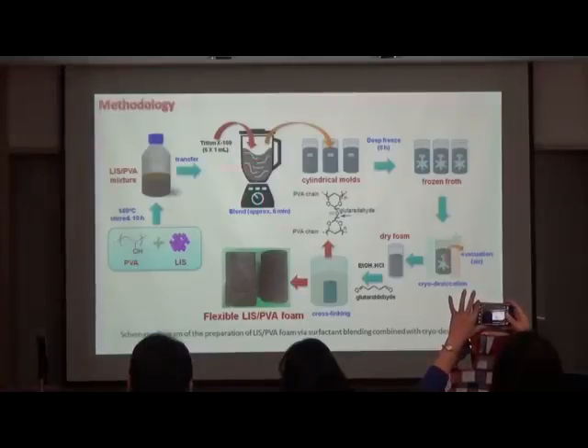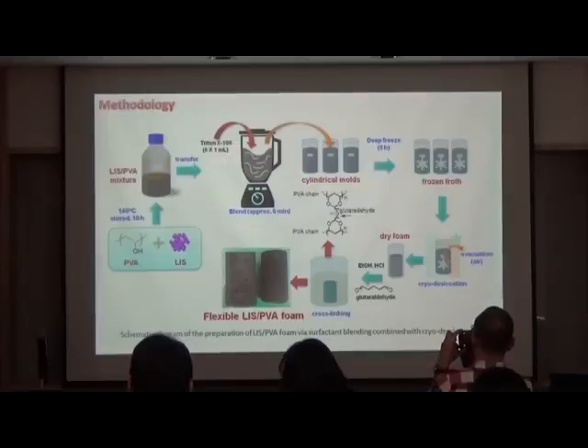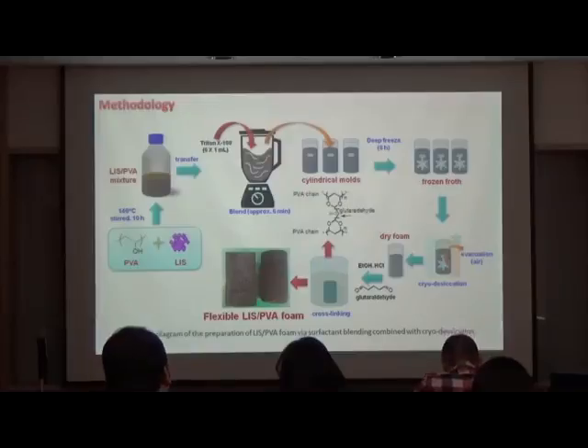After addition of 6 ml of surfactant, the froth was then transferred to plastic cylindrical molds. The froths were then frozen and cryo-desiccated to dehydrate the foams by sublimation of ice crystals. Acid-catalyzed cross-linking of the PVA of the foams produced was then done by soaking the foam in a solution composed of glutaraldehyde as the cross-linker, hydrochloric acid as the acid catalyst, and ethanol and water as the solvent. The samples were then thoroughly rinsed to remove the residual cross-linking solution and finally dried.